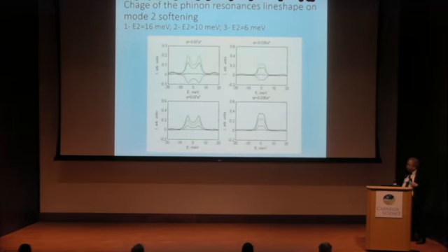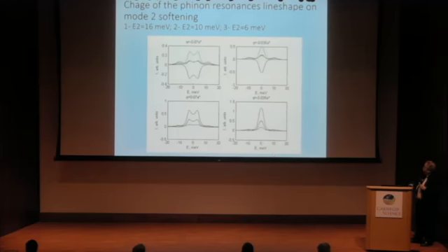So we can try to follow the Fano line shape. It's interesting to look here. On one side, for instance, E2 is still very high in intensity. On one side of the zone boundary, we have a picture like this, the black one. On the other side, very similar. But finally, closer, you see already a large difference between the frequency of one mode and the other. We see a very strong change. On one side the intensity is rather low, on the other side it's much higher. Finally, we see a huge central peak on one side of the endpoint and nearly nothing on the other side.